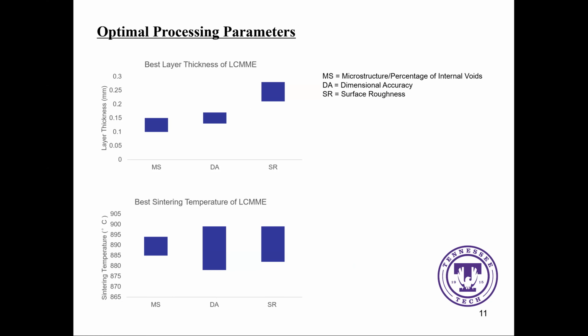Also, we use response surface methodology to find the best manufacturing parameters in the low-cost metal material extrusion. For the optimal processing parameters, for the best layer thickness, if we want to have a small internal void, the layer thickness should be around 0.1 to 0.15 millimeters. But if we want to have a very good surface roughness, the layer thickness should be around 0.2 to 0.27 millimeters. So in real world applications, if you want to have a very small internal void, minimize the layer thickness. If you want to have good final results of the surface roughness, just increase the layer thickness.